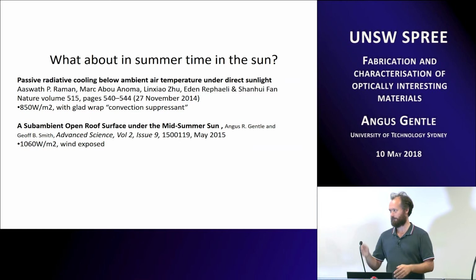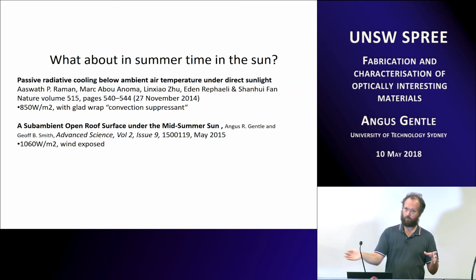So as soon as the paper came out, we turned around and started to do the experiment that we'd been planning to do for quite a while. So their one, basically, was at the time of the year where you got about 850 watts per square metre onto the surface. And they had a convection suppressant over the top to make sure you don't get wind warming the surface back up. So that was the two things on that one.